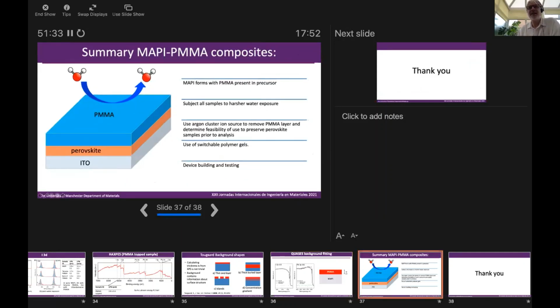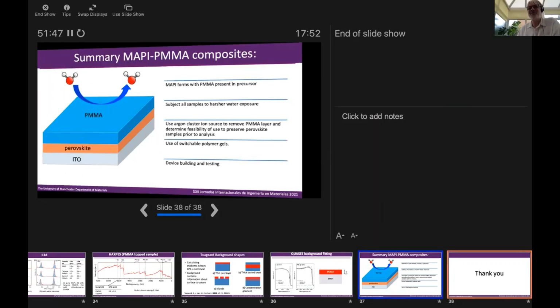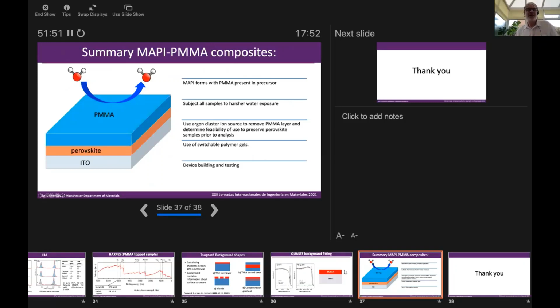So just to summarize this particular short experiment, we found that MAPI forms with the PMMA present in the precursor. The work we want to go on to is to subject all the samples to some harsher water exposure, for longer times. We also want to investigate the possibility of using this PMMA capping layer to transport samples for analysis by other techniques or by other synchrotron systems for other photoelectron spectroscopy measurements, maybe to look at the valence band. The idea would be that we can cap with PMMA and then use an argon cluster ion source, which is a gentle etching that you can have fitted in photoelectron spectroscopy instruments. This can then remove the PMMA and allow us to look at fresh perovskite rather than perovskite which has been exposed to atmosphere, because the degradation that occurs in this perovskite is almost instantaneous as soon as it's exposed to water vapor.